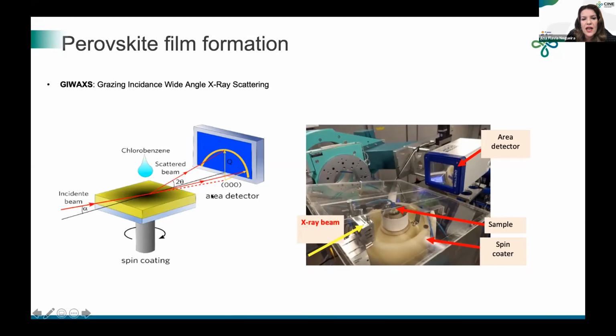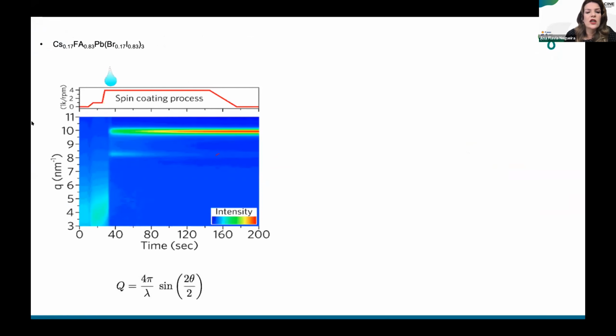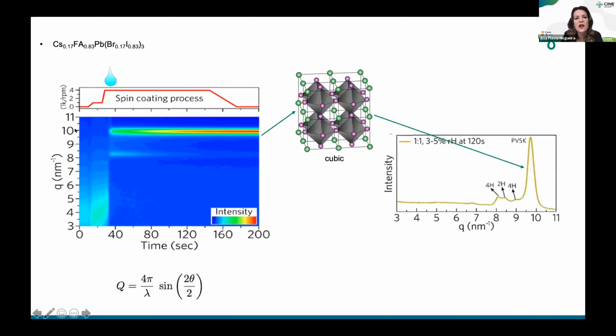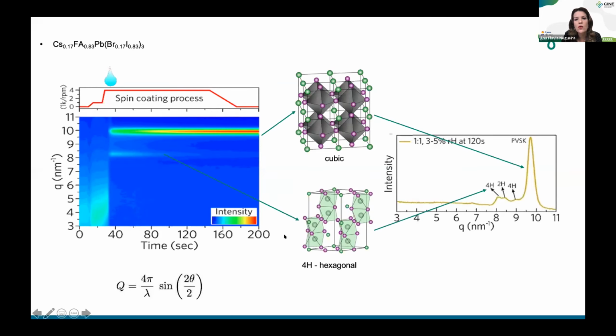So this is the data that you can get from this. This is a 2D image, and then you can also plot your data in this form, like Q as a function of time. Remember that Q is related to theta. As you can see in this data, as soon as you drop the anti-solvent, you start to see the formation of a very strong peak at Q equal to 10, and also the formation of other peaks that are going to disappear with time. We assign this strong peak at 10 nanometers^-1 to the cubic perovskite. This is the phase that we really want. And those other peaks we assign to these 2H and 4H hexagonal phases.